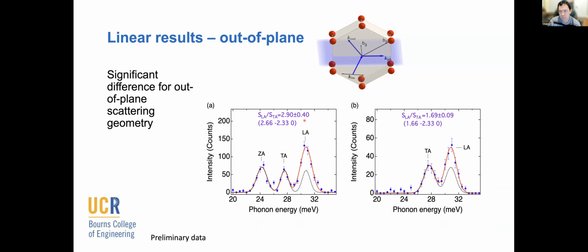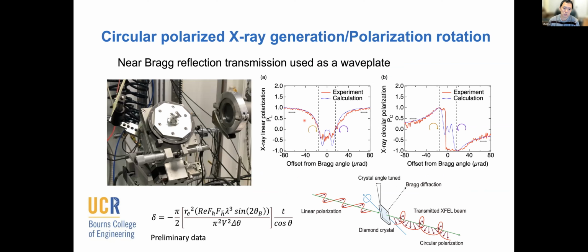So what we ended up doing is we thought it might be a good idea to see how the X-rays scatter with circularly polarized X-rays. And this is what we ended up trying to work with in X-ray scattering using an X-ray polarizer. This is a polarizer we use with the help of Thomas. And it actually works pretty nicely by having a diamond crystal aligned almost to the Bragg condition, but off-tuned slightly.